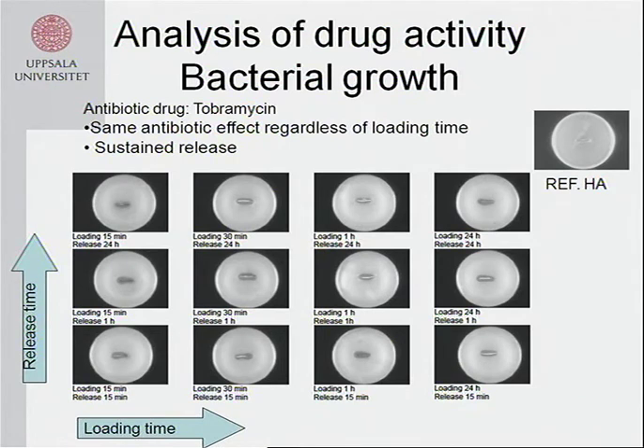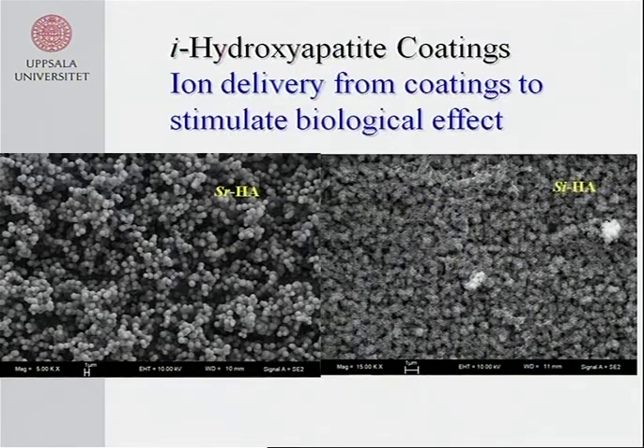In this case, what you see here is the inhibition of bacterial growth. So this was the reference HA coated, and these are coated plates, and you see the inhibition zone of bacterial growth around the plates. What we have measured now, these are for loading of 15 minutes, and the release time in this case is 1 day, but we have measured for up to 1 week. And we still see an effect of that. So you load for 15 minutes and you get a slow release for a longer time from this type of coatings. So it's what we call a sustained release type.